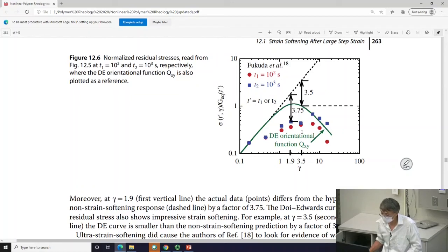Basically reading that relaxation at different times, you can see they are non-monotonic, right? Beyond a certain stress, the stress you produce actually is lower. Non-monotonic. So that's the careful analysis of the data we had. Okay, how can this be? You strain a small amount, you wait. And you strain a larger amount, you wait for the same amount of time. You find the stress involving a large amount of strain after you wait for a certain time actually was lower.